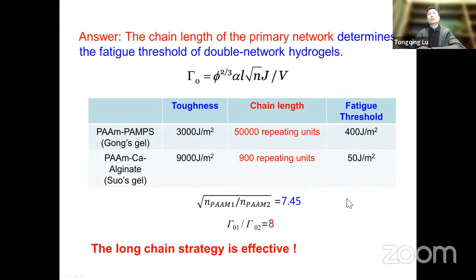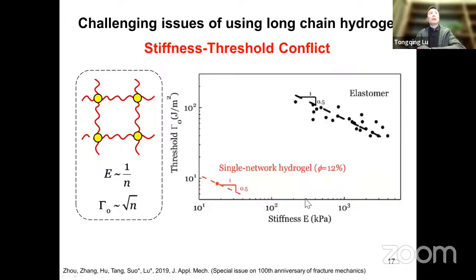So after these experiments, we can confirm that the long chain strategy is very effective. Means if you want to improve the fatigue threshold of a double network hydrogel, you need to make the chain length of the primary network very long. Then you can improve the fatigue threshold. But there's also a challenging issue if we want to use long chain hydrogels. Actually, this issue not only exists for hydrogels, but also for a wide class of rubber. So it's called stiffness threshold conflict.